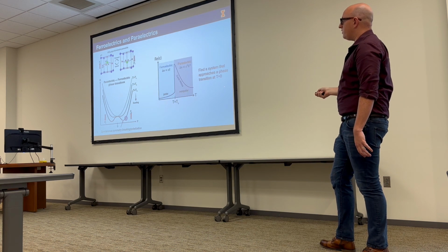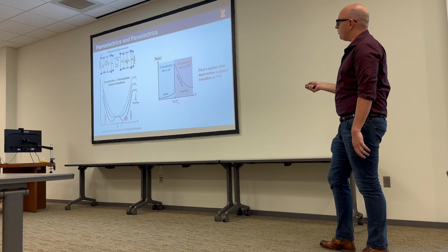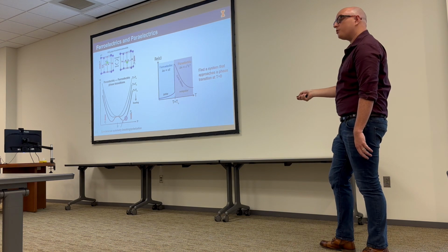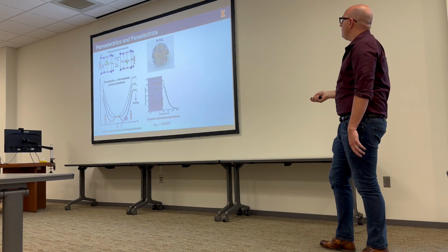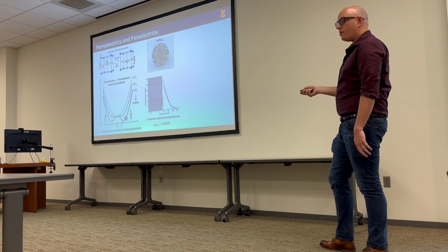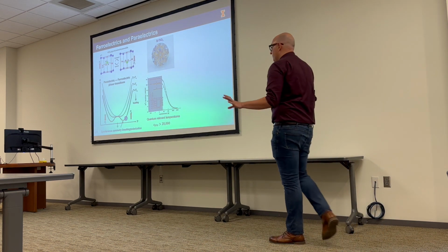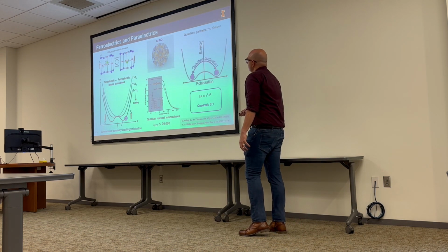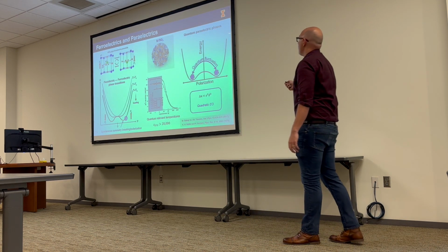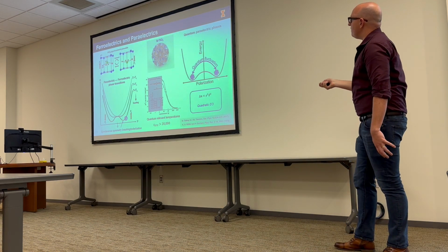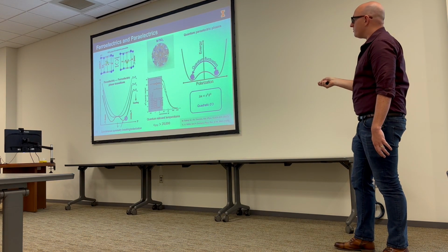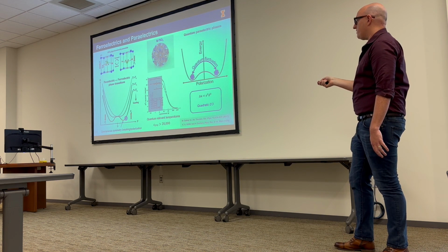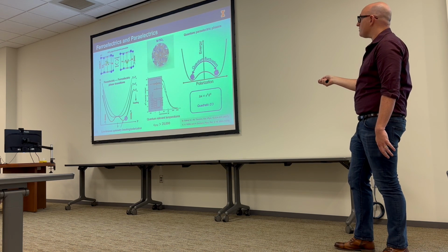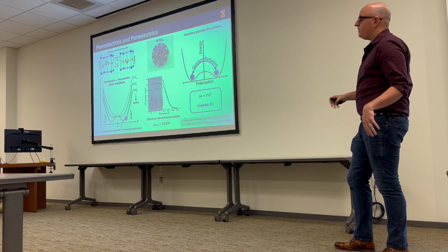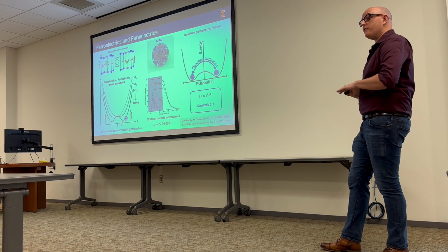So I told you here, you approach this phase transition, your dielectric constant explodes, but then of course you drop into one of these wells and then it goes down again. In this case, it goes up, and basically no matter how cold you go, it never crystallizes. It never undergoes this phase transition. So this is sort of cool. This is related to something called the quantum paraelectric phase in strontium titanate. Basically, instead of dropping into one of these two potential energy wells, this barrier is so small and this mode is so floppy that zero-point fluctuations always bounce you back and forth between these two wells, and you never actually crystallize a phase. So you're always continually approaching a phase transition, but you never reach it.